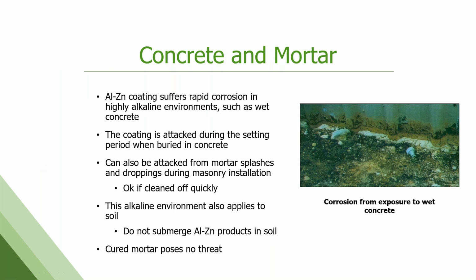Concrete and mortar, big problem out in the field. Aluminum zinc suffers rapid corrosion in contact with wet cement or concrete. It's during the setting process or when buried in the concrete. You want to make sure there's a barrier between those two things. Mortar splashes can be problematic, right? If the mortar or dropping splashes get on there, you want to clean it off very, very quickly, or it won't come off, or it'll leave a spot of corrosion. And again, don't use aluminum zinc products submerged in soil. Don't use it for culverts or potting plants or signage that's going to go in the ground, anything like that.